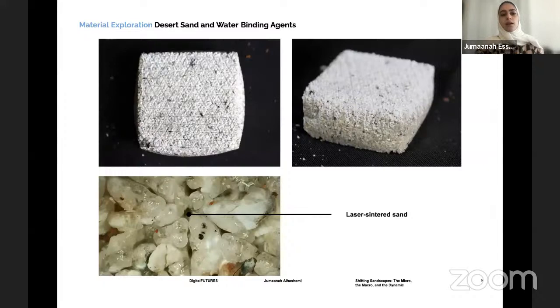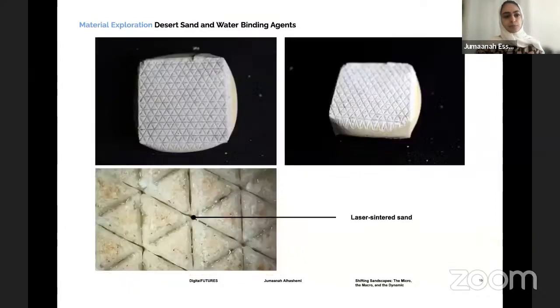And then after that, I wanted to see if there's possibly a way to fuse the sand together while also creating the sintering process. In this case, I also worked with water-based agents, specifically sodium silicate. What I did was as simple as going through hatching patterns that are sintered by the laser. And as you can see at the bottom, it's the glass that is trying to emerge while also keeping it bonded.